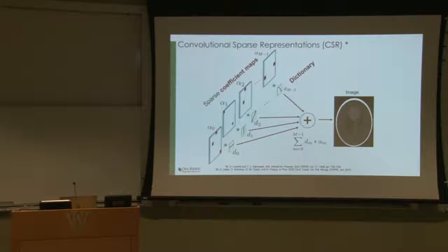We have been interested in a model called the convolutional sparse representation model. It's a model for an image. It says that a good model for an image is that it can be approximated as a convolution between a kernel and a coefficient map. And what you're seeing here is regions where this particular kernel is active. By summing this up, you can get an image. This is the underlying signal model. It's a convolution between a dictionary and a coefficient map which has the size of the image.